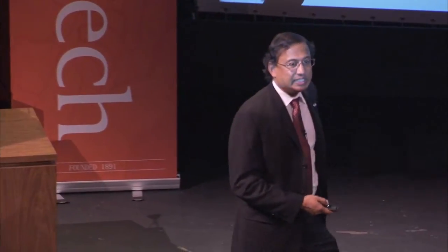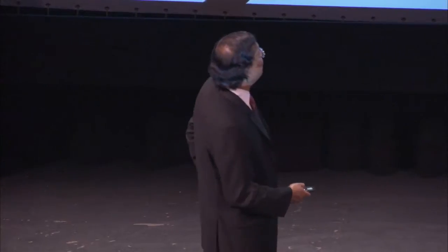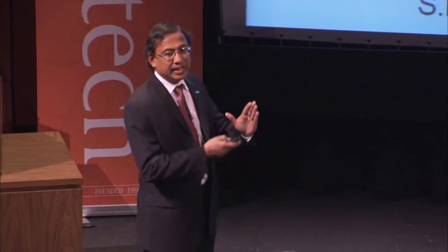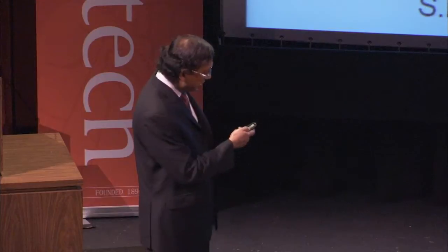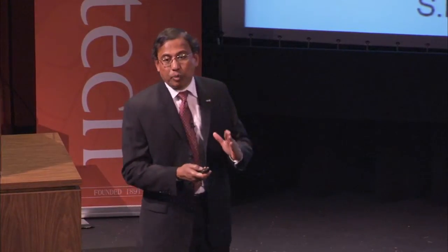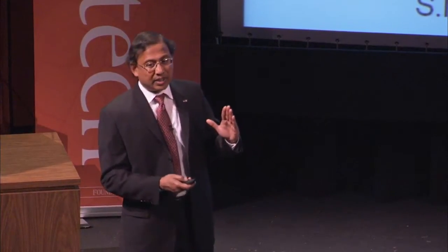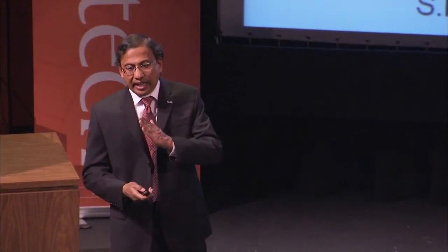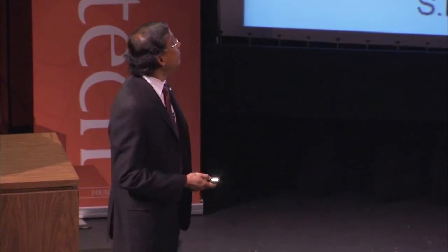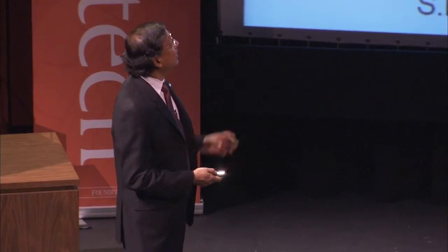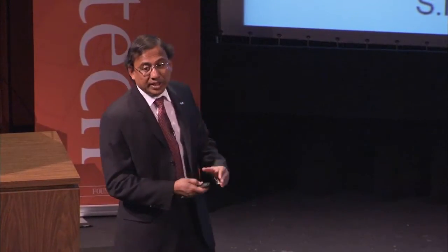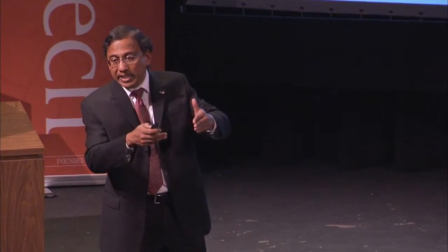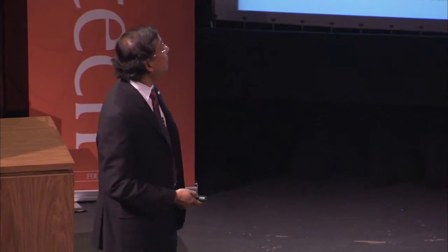So you can see this is the idea of the bulletproof glass. The bulletproof glass is nothing but layered material. So they have clear layers of materials. One is glass, the other is some polymer. So they have a very stiff material and a soft material. So these are layered. And when the bullet impacts the plate, the projectile is stopped because of the damage which occurs, because this material is more compliant and causes the material to deform.